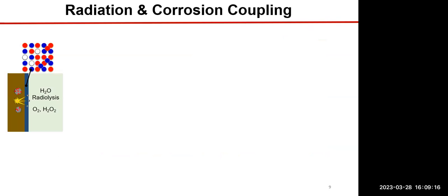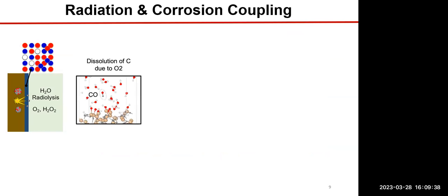And besides that, as we know, the cladding material in nuclear reactors will not only be damaged by neutron radiation, but can also be corroded by the coolant environment. Neutron radiation will not only induce defects in the cladding materials, it can also induce the radiolysis effect in the coolant environment, producing some products like oxygen gas. And our previous simulations found that the existence of oxygen gas in the water environment can definitely enhance